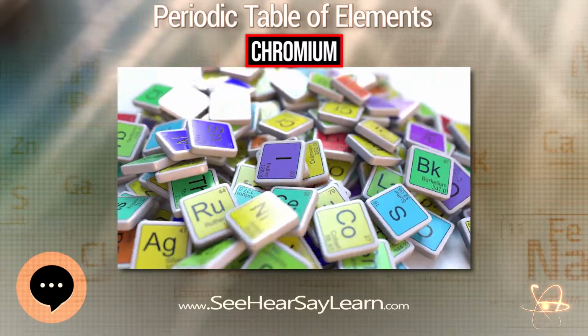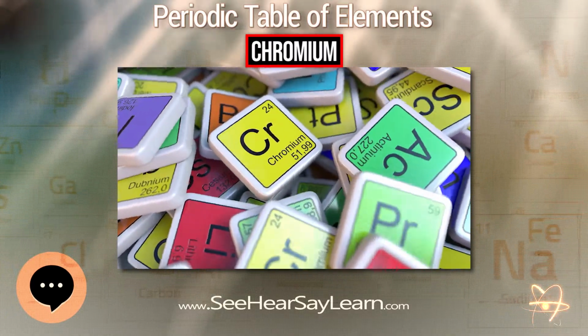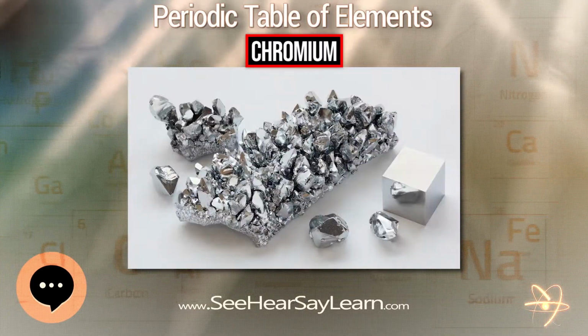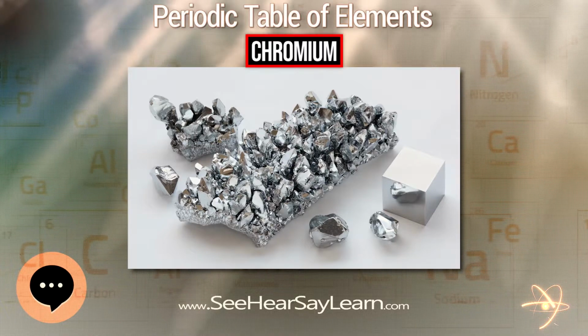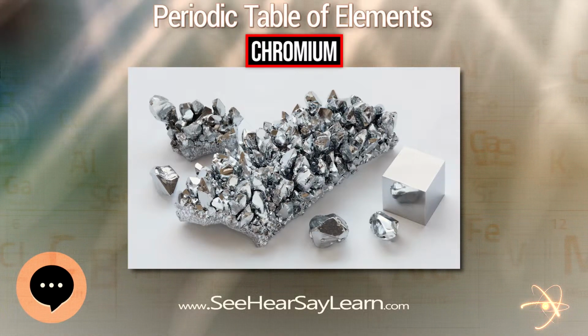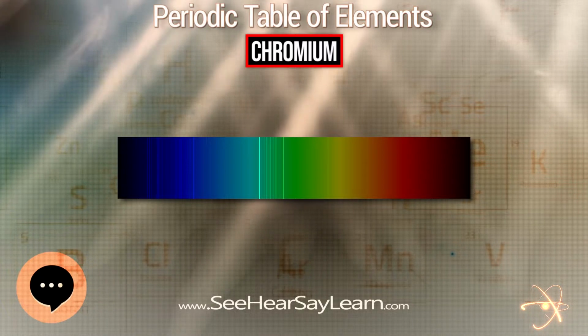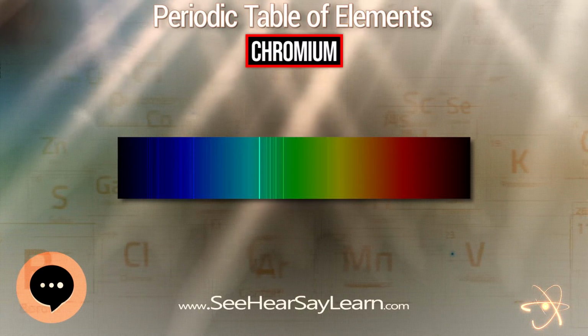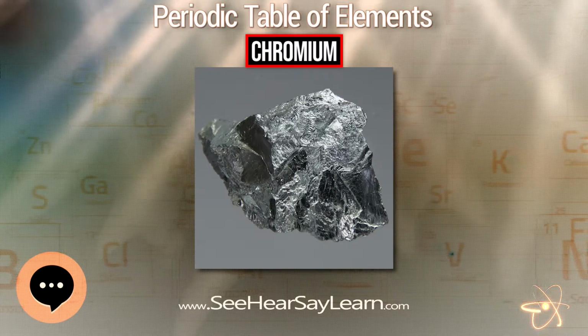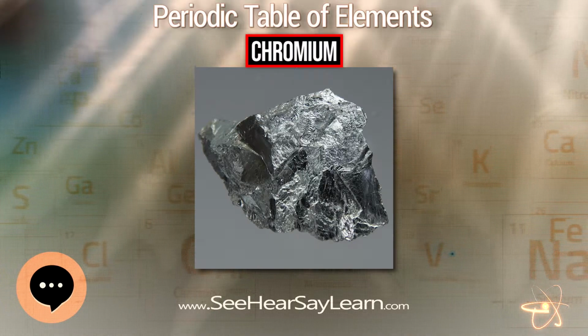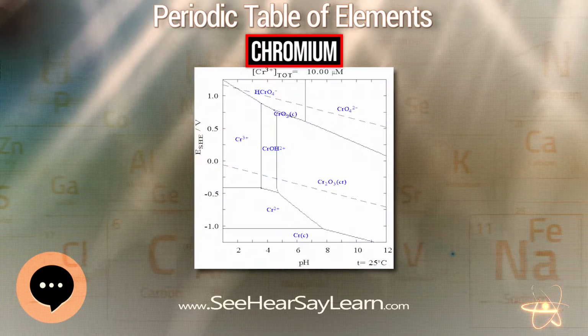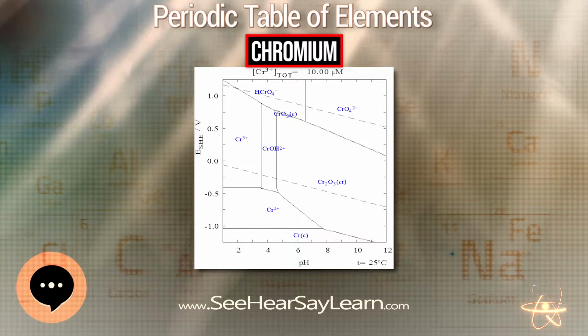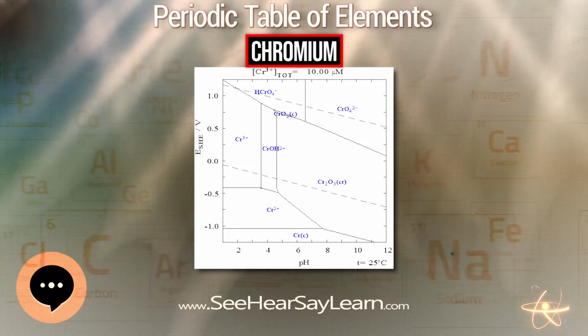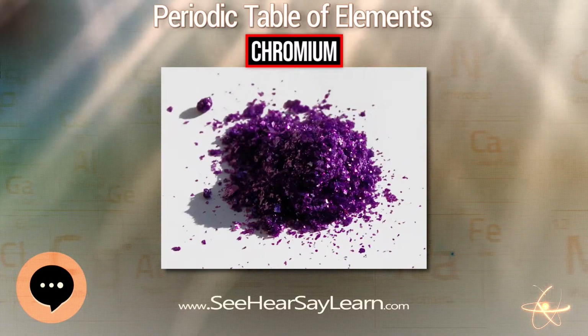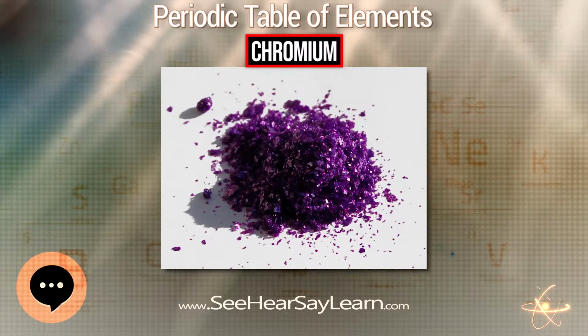In the chromate conversion coating process, the strong oxidative properties of chromates are used to deposit a protective oxide layer on metals like aluminium, zinc, and cadmium. This passivation and the self-healing properties, through the chromate stored in the chromate conversion coating, which is able to migrate to local defects, are the benefits of this coating method. Because of environmental and health regulations on chromates, alternative coating methods are under development.